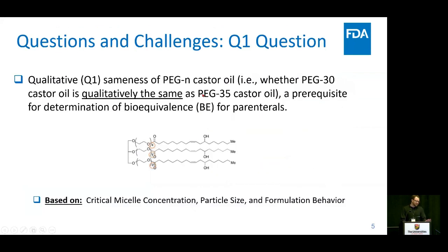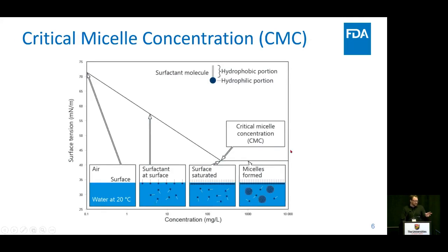Basically what we're looking at is most of these products have a PEG 35. You can control the ratio of the ethoxylated region here in the castor oil by varying that mole percentage. And so the question is, are all the CAS numbers, so the PEG 30 through 40, qualitatively and quantitatively the same within these formulations? We were assessing that based on things like critical micelle concentration, particle size, and their formulation behavior.